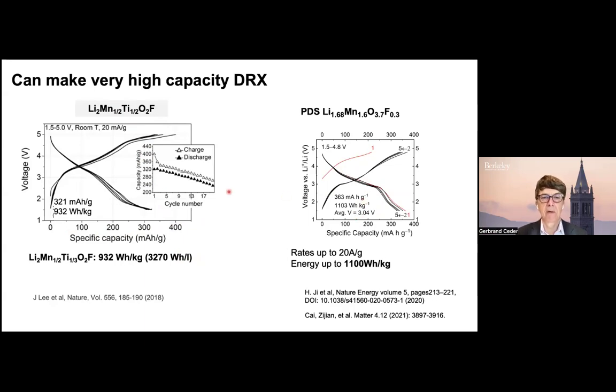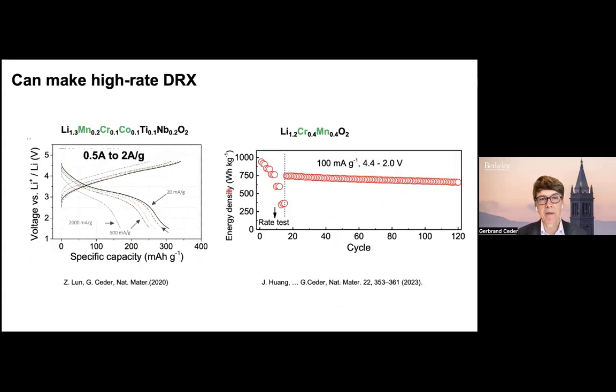These materials are exciting proofs of concept. They're certainly, in some cases, challenging to work with, and I'll come back to that because towards the end, I'll go towards the more practical DRX materials. You can make high rate DRX. A lot of DRXs still have fairly poor diffusivity, but that doesn't mean that all of them do. If you do high entropy ones, you see discharges up to 0.5 amp, 2 amps per gram. If you do slightly more partially disordered materials, this is a chromium manganese, here's a discharge at 100 milliamps per gram.